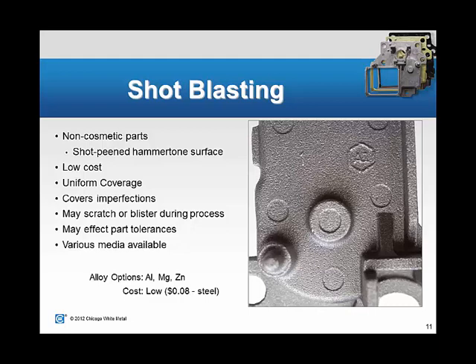So we would consider this a mechanical finish for a non-cosmetic part. It's going to give a nice, even, uniform coverage at a low cost, but we would not consider this a really highly cosmetic look. It does help cover imperfections in the surface that I mentioned. Potentially, depending on how aggressive the shot is to the part, you may have scratching or blistering that occurs during the process, so it's something to keep in mind, and your die caster should help control that.